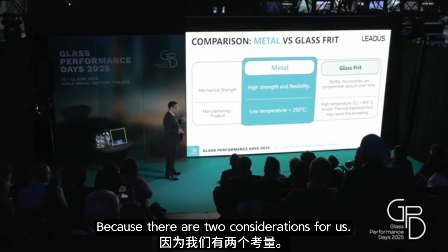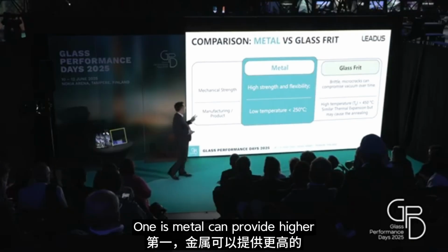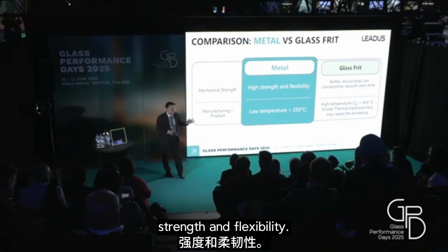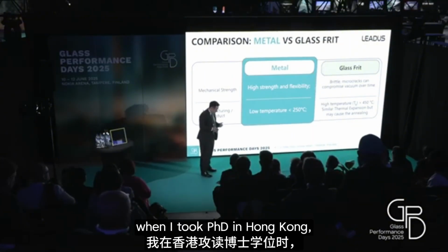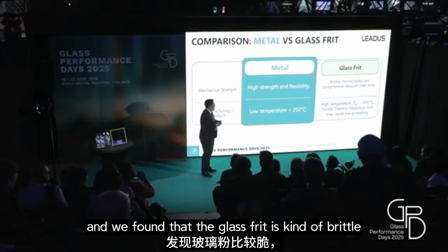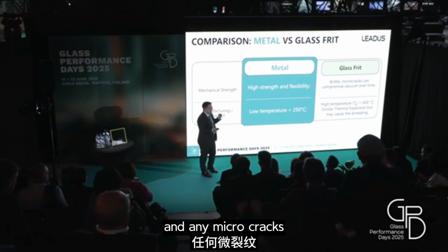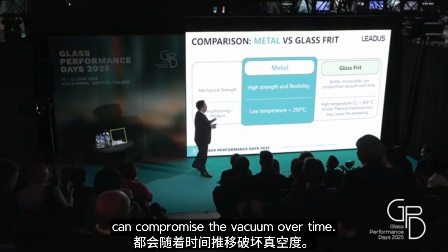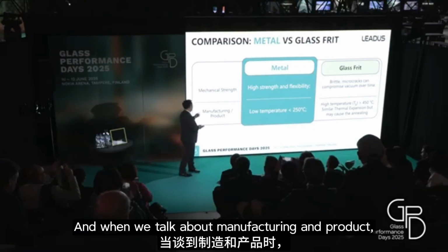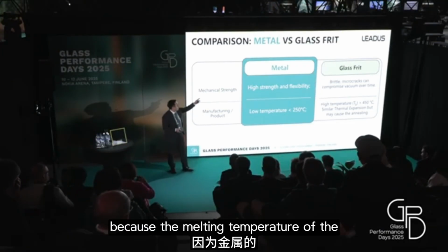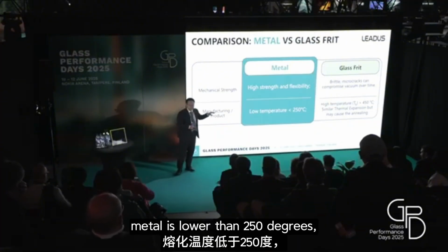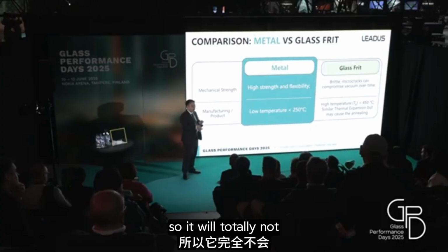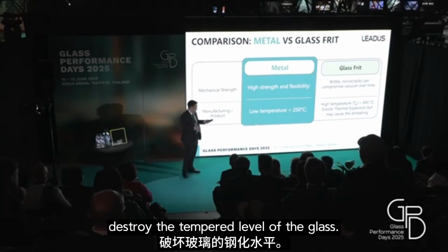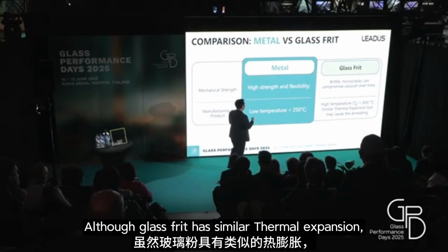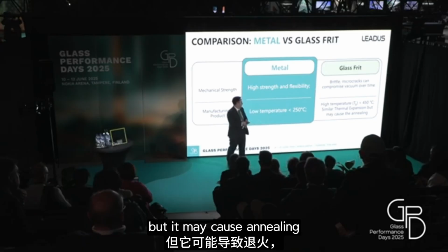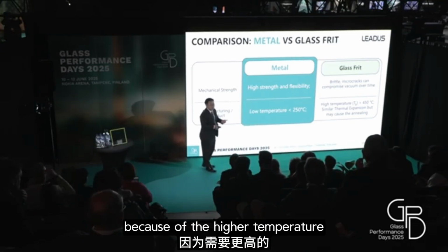But why do we choose metal, not glass frit? Because there are two considerations. One is that metal can provide higher strength and flexibility. When I did my PhD in Hong Kong, we tested all sorts of materials, and we found that glass frit is kind of brittle, and any micro cracks can compromise the vacuum over time. And for manufacturing, the melting temperature of the metal is lower than 250 degrees, so it will not damage the glass at all. Also, glass frit has similar thermal expansion, but it may cause annealing because of its higher melting temperature.